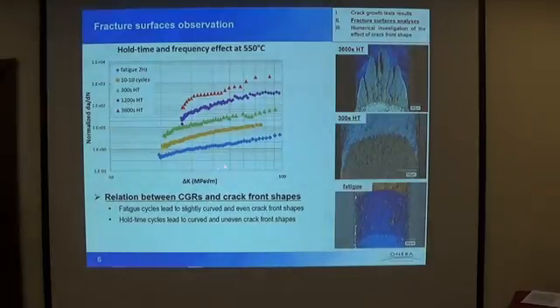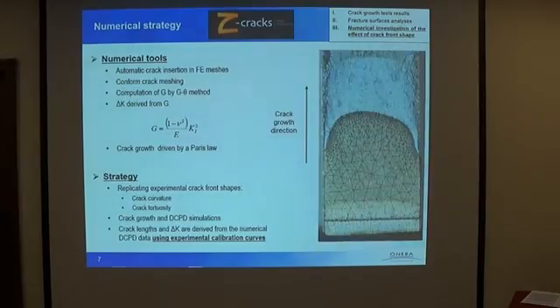The results I have presented previously were analyzed assuming a straight through-thickness crack for the DCPD crack length measurement and delta K calculations. As you can see, if we apply a 2 Hz cycle or a 10-10 cycle, this is a good assumption. But if we apply a hold time cycle, the hypothesis of a straight through-thickness crack is not valid. So we will investigate this effect numerically.